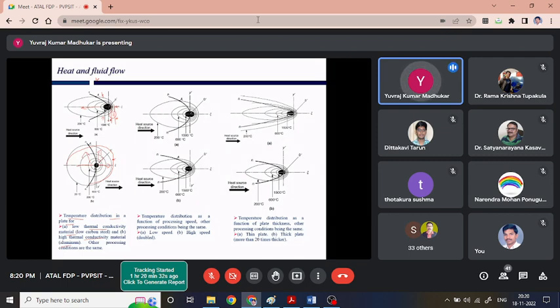With respect to the speed of deposition, for low speed and high speed of deposition, we can see that in case of low speed, the area in the lateral direction is relatively higher. In the front also, a good amount of heating takes place. If we increase the speed, the length increases significantly. However, the front heating reduces significantly.